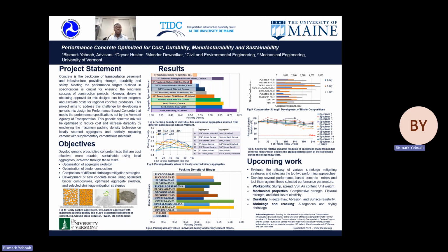Also, in some cases, the concrete producers experience delays in obtaining approval for their concrete mixes, which can hinder the progress of their projects and escalate costs. So, this project aims to address this challenge by developing a generic concrete mix design for performance-based concrete that meets the performance specifications set by the Vermont Agency of Transportation. This generic mix will be optimized to reduce costs and increase durability by employing the maximum packing density technique on locally sourced aggregates and partially replacing cement with supplementary cementitious materials. This mix design will help reduce carbon footprint and can easily be adopted anytime a producer experiences delays in approval of their mixes. So to achieve this objective, these tasks will be undertaken.